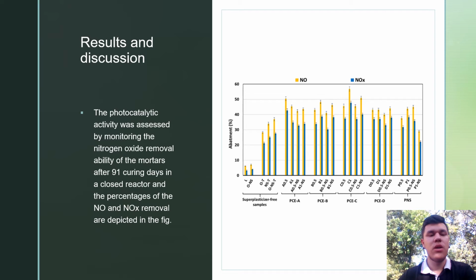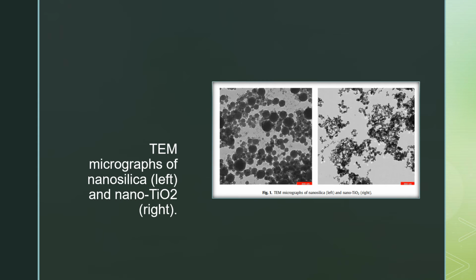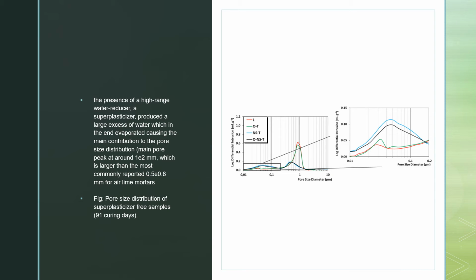Results and discussion. The photocatalytic activity was assessed by monitoring the nitrogen oxide removal ability of the mortars after 91 days of curing in a closed reactor. The presence of high range water reducers and superplasticizers produces a large excess of water, which in the end evaporates, causing the main contribution to the pore size distribution.